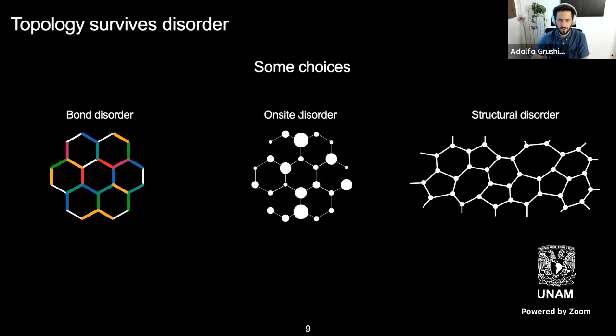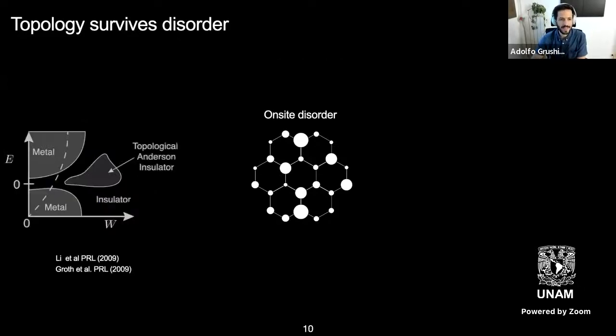And in fact, just as a zeroth order definition, an amorphous material is one where all of these disorders appear at the same time. That means there's no translational invariance, there's no long range order, and also the energy scales are fluctuating in space. Now, what's interesting is that already in 2009, people realized that, for example, on-site disorder acting on a crystal can get you from a trivial insulator to a topological insulator.